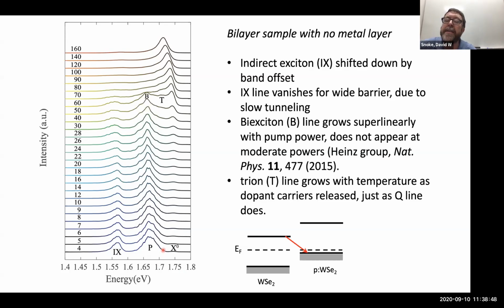Certainly if the bi-exciton has an energy in that region, it would lead to more complications because you'd potentially have two lines in the same place. But I think you can still distinguish them by going to low power, because the bi-exciton line simply goes away at low power. I also have to say, Bondarev did the theory for the bi-exciton, the same theory that does all this, and he got agreement with Tony Heinz's result. So I'm a little surprised that that's being reinterpreted, but science moves on, so that's certainly possible.